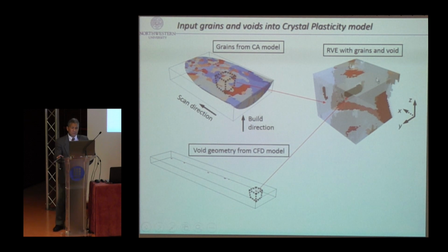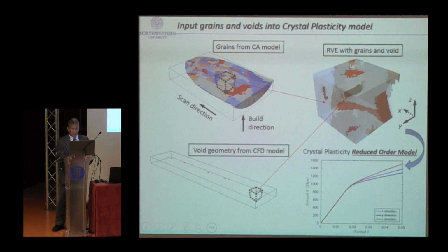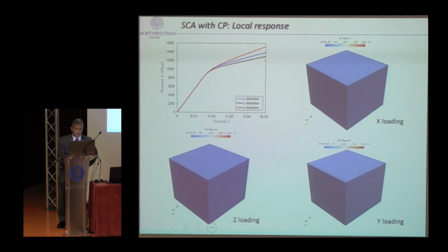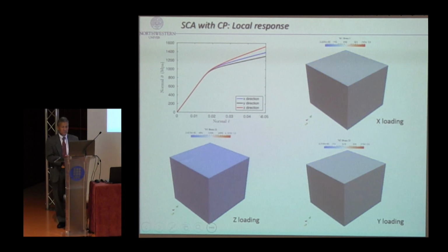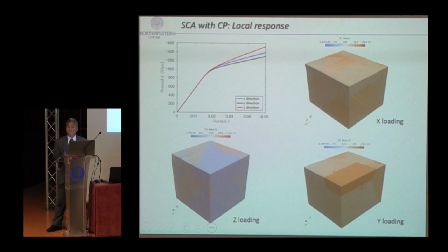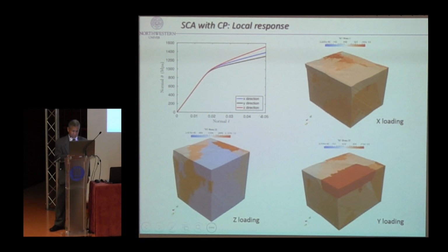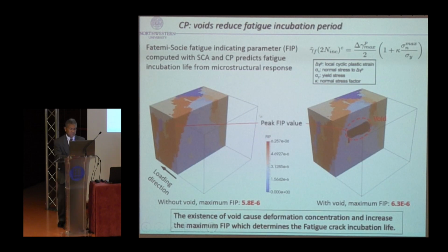You basically will look at the grain orientation, that's crystal plasticity, and you have the void formation, minimize it, and now you can actually look at using the reduced order model, which I talked about, SCA, look at crystal plasticity, and you can see here, when you actually test it out in different directions, you get different stress strain laws in this case. But we computed on the fly, based on the experiment, based on the computation in this case. Now we also do experiments.